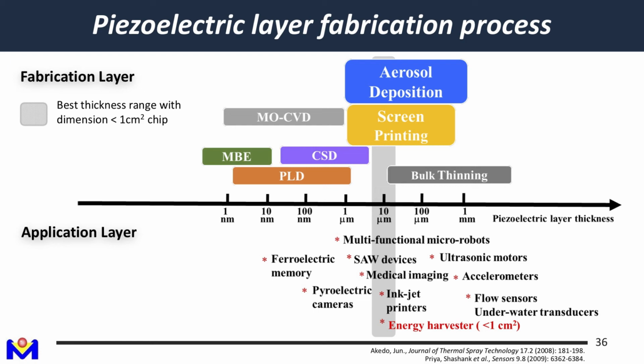If you touch it, it will break. Okay, so the bulk PZT ceramic material thickness is limited to about 100 or 120 micron. For thinner ceramic plate, it will break. So a lot of researchers are working on starting from like 100 or even 200 micron bulk PZT material and polishing it, thinning it to around 20-30 micron. But it also has certain limitations.